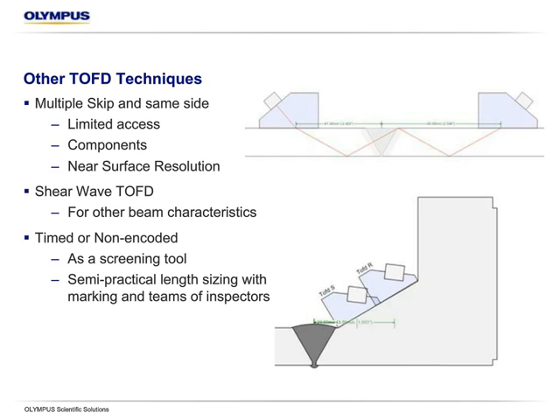Other TOFD techniques, there's a chance to do multiple skip where we're actually sending the sound in and it's bouncing off the various interfaces multiple times. This is actually done when there's a limitation in access or there's a component in the way. It can also be used just to improve the near-surface resolution. Not so popular, but it does happen. Same with same-sided access. So we can actually position the TOFD probes on one side of the component and try to get a diffracted signal back. Again, very difficult to plan out compared to double-sided access, but it is done in some special applications.